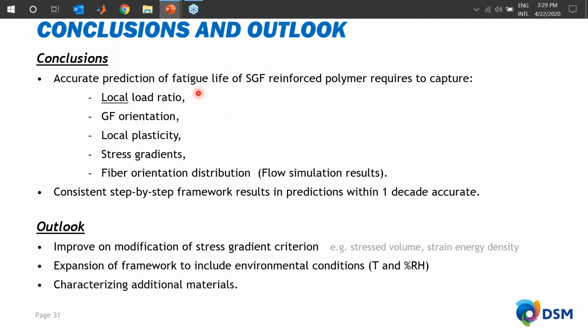But I think in all fairness, where we really make a step up is predicting this load ratio dependency, because it was really important to get the prediction on part level well. And also this local plasticity combined with stress gradient is really key to make a consistent bottom-up approach to predict a lot of different geometries and eventually also end up with predictability on part level. So I would say the local load ratio is key, local plasticity and gradients. And for the fiber orientation, we just use the state of the art, but I think that is not that much improved by our efforts.